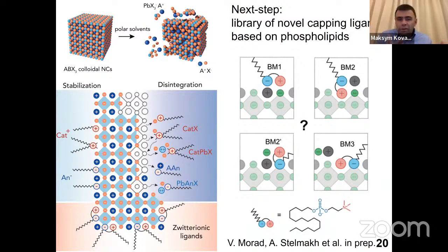Now, as you've seen, when we use alkylammonium ligands, they do bind non-covalently. They replace cesium, as we discussed before. Such alkylammonium displaces a surface cesium ion and inserts the head group into this pocket. A similar approach you can do with anionic ligands. They will displace surface halide and insert themselves. But an even bigger problem is that it's easy to overdo this, because as you add more of these ionic ligands, they start carving into your material, they etch it. And it's always tricky to find the balance.